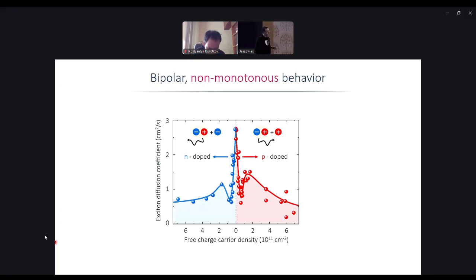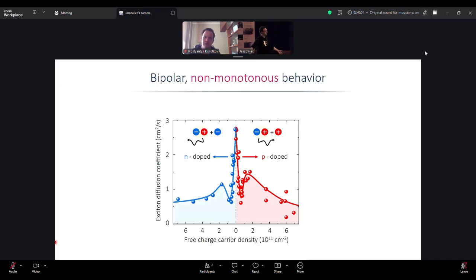Very quickly, what you see in this figure, this is, by the way, not a singularity at zero. It doesn't diverge; you just reach a phonon-limited case. Initially, in this regime, you add more electrons, excitons scatter with electrons, and the diffusivity decreases because you add a scattering channel. Right here, where this curve becomes non-monotonous, you start to have trion formation. A trion is a three-body state, two electrons and a hole, or you can think about it as a Fermi polaron, where the exciton carries the polarization of the electron Fermi sea.